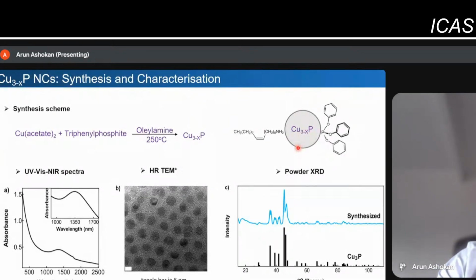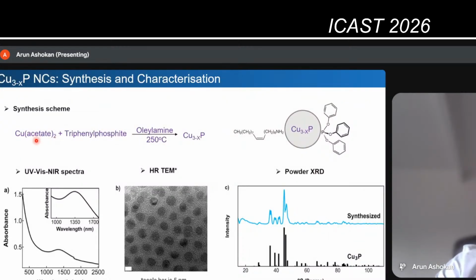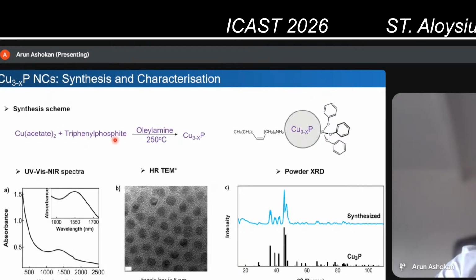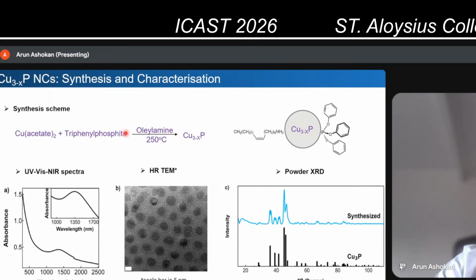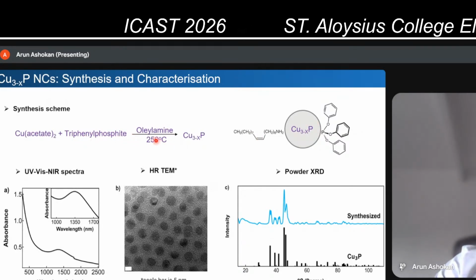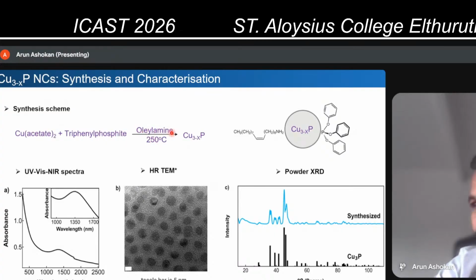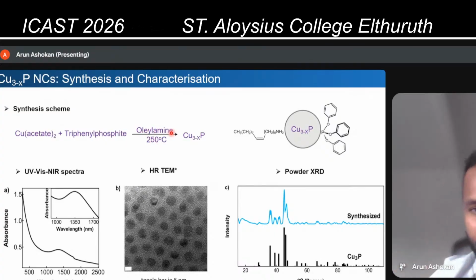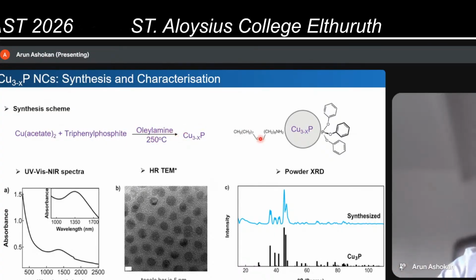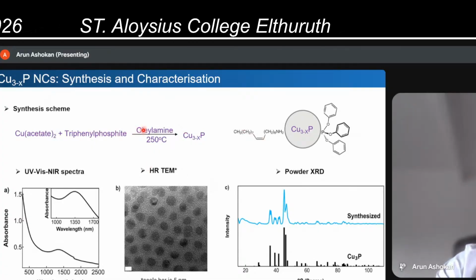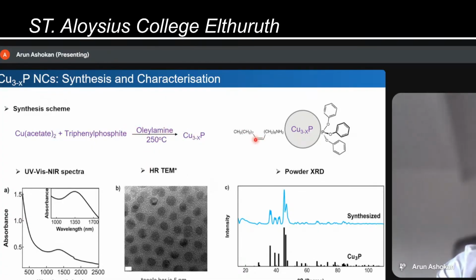To synthesize these nanocrystals, you take copper acetate and react it with triphenyl phosphite as the phosphorus precursor and heat it up to 250 degrees Celsius in oleylamine. This oleylamine acts as a ligand and also as a reducing agent because it has a double bond, so it can donate electrons.